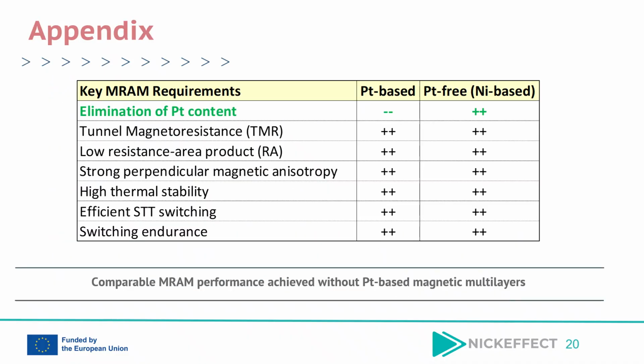This appendix summarizes the key MRAM performance requirements and compares conventional PT-based technology with the developed PT-free cobalt-nickel-based approach. The presented results demonstrate that the PT-free MTJ stacks can achieve performance comparable to state-of-the-art PT-based MRAM while eliminating the need for platinum group magnetic multilayers.